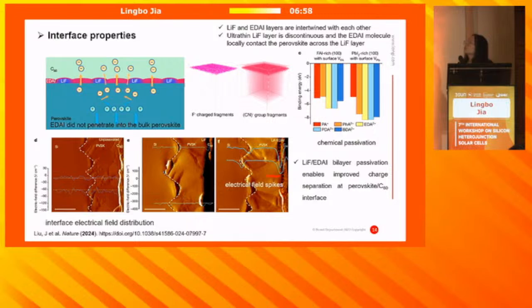Next, in order to prove the interface properties of our materials, we first use ToF-SIMS measurement to monitor the distribution of these materials. We have also used other strategies to confirm the distribution of these materials, but due to the time limitation, I just show the ToF-SIMS measurement. From this measurement, we can notice that the EDAI molecules did not penetrate into the bulk perovskite, and lithium fluoride and EDAI materials are mainly localized at the surface of perovskite films, and they are intertwined with each other.